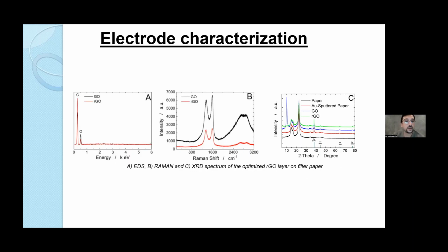The electrode has then been physico-chemically characterized, and we have carried out EDS, XRD, and Raman analysis in order to find out the degree of reduction of graphene oxide. As it's possible to see, EDS analysis after the reduction of graphene oxide shows a much higher peak for carbon and a lower peak for oxygen, demonstrating that the electrode has been reduced. The same results were given by the XRD and the Raman spectrum, but with all those analyses, we were not able to find out the degree of reduction.